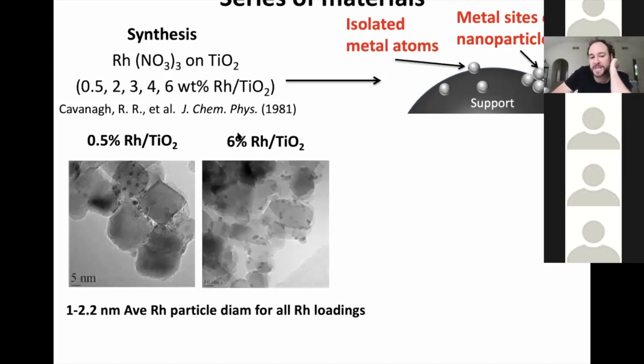So we made a series of materials, and the first thing that we looked at is at the lowest weight loadings of rhodium and at the highest weight loadings of rhodium, we found relatively similar average rhodium particle sizes. So this was important to us because we knew as we were varying loading, maybe we would vary the relative fraction of these two species, but we might also change the nature of this one, making it larger, making it smaller, exposing more steps and edges or exposing more terraces, and having really two different ways we were influencing the potential chemistry. But the fact that the particle sizes were relatively similar across the whole weight loading allowed us to then just focus on whether or not a subpopulation of atomically dispersed or single atom rhodium species were causing differences in chemistry.